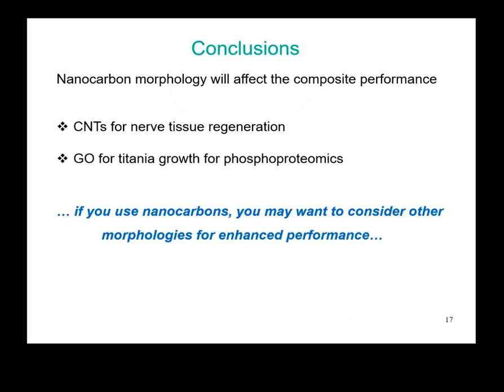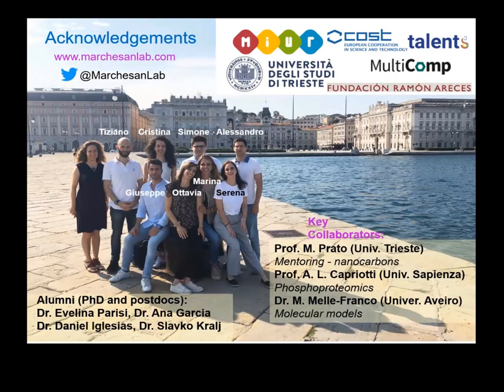So concluding, yes, nanocarbon morphology will definitely have an effect on the composite performance. And this is something that is not always obvious to anticipate a priori. We've seen the example of carbon nanotubes for nerve tissue regeneration briefly, and also of graphene oxide for the growth of titania nanocrystals, so ensuring a high surface area for good interaction with phosphorylated peptides, as applied to phosphoproteomics. And that's all for my talk.